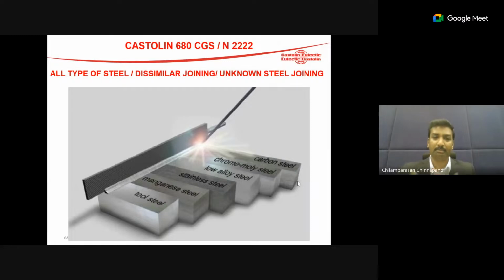So one electrode, in a process industry, you cannot keep different electrodes in stock for all these different products. One electrode can do all this welding, called 680 CGS, for 3 layers up to 15 mm, where the temperature is low. If the temperature is very high, up to 1000 degrees, in furnaces and other places where cracks keep coming again and again, you can go with our 2222 and you can forget the crack. Once you do this crack repair, you can forget it. You'll never get the crack again in this component.